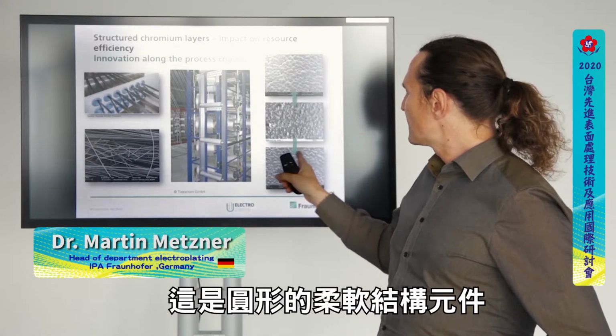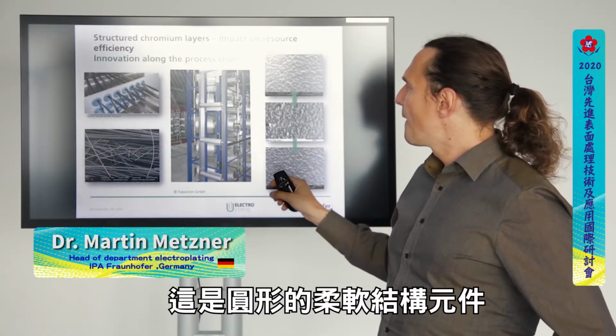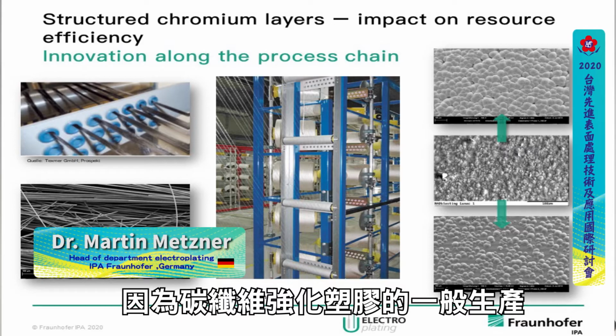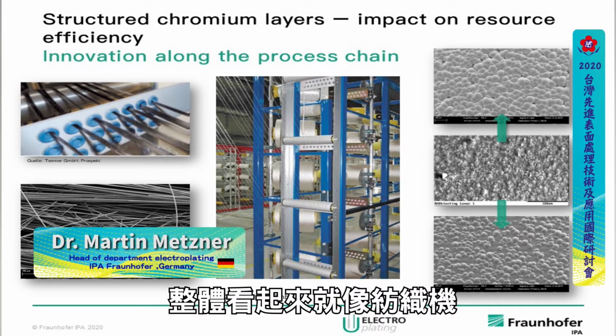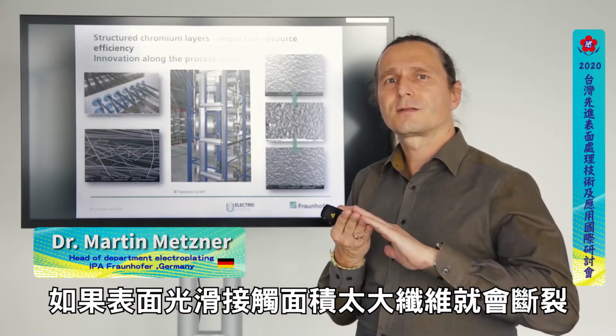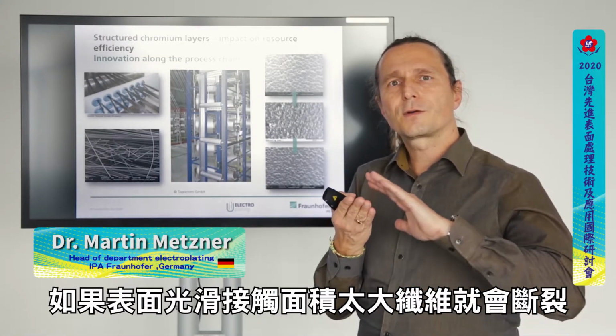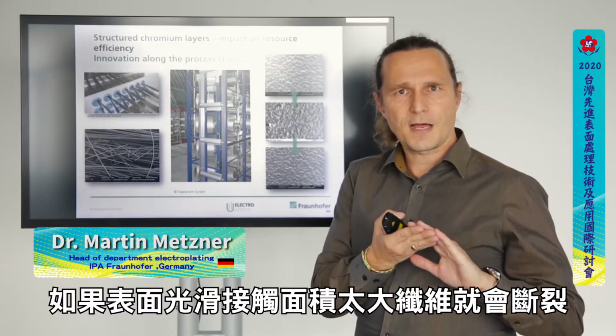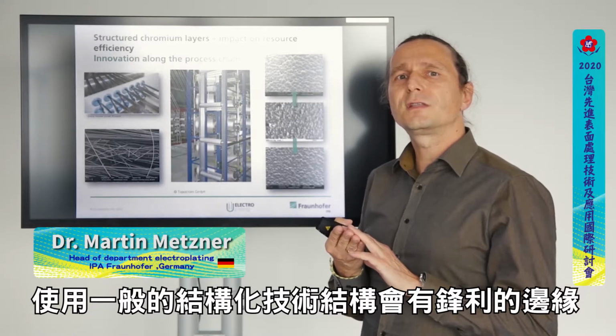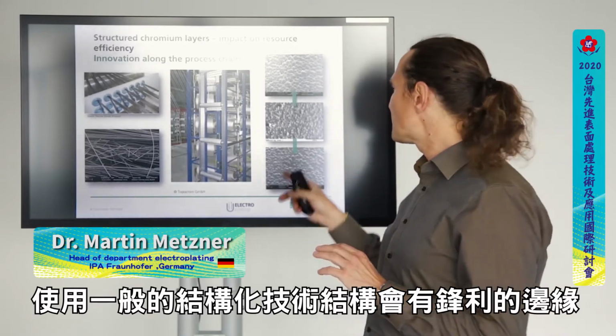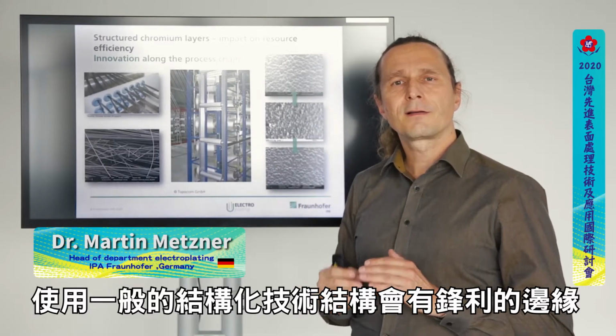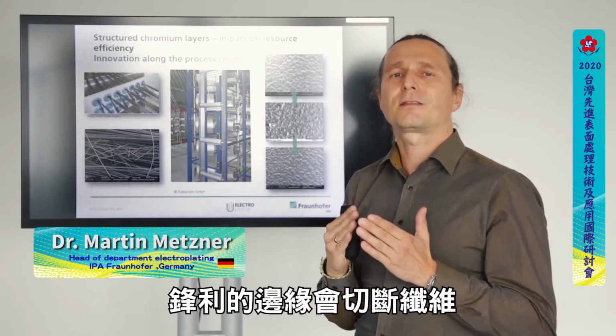It's this soft structure element with the round shape, because when you go into the normal production for carbon fiber reinforced plastic, you've got a lot of contact points. In fact, the whole thing looks like textile machines. And when you've got polished surfaces there, then the contact area is too large. The fibers break. When you structure this with normal structuring technologies, with sharp edges in there, then you've got sharp edges and they cut the fiber.